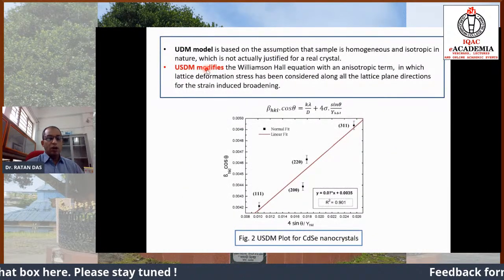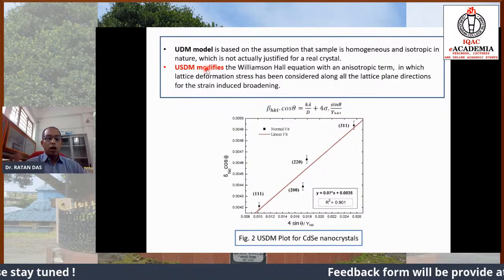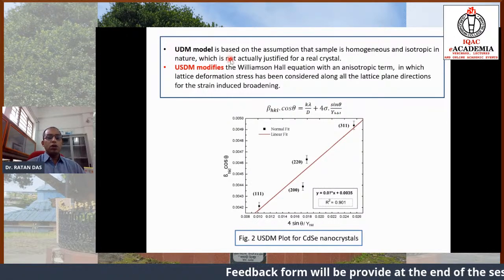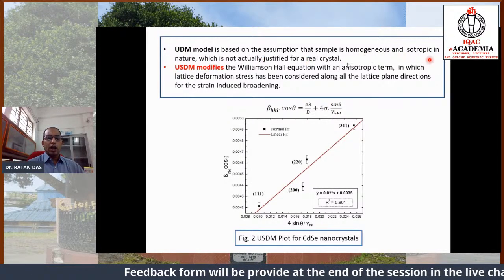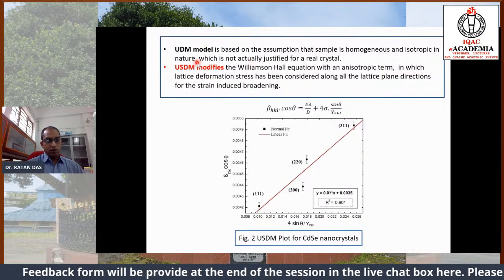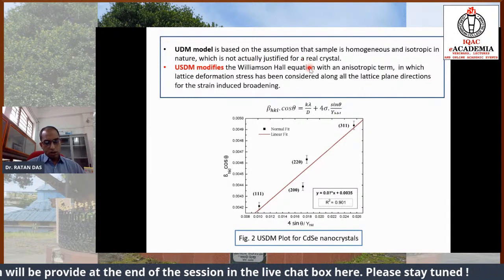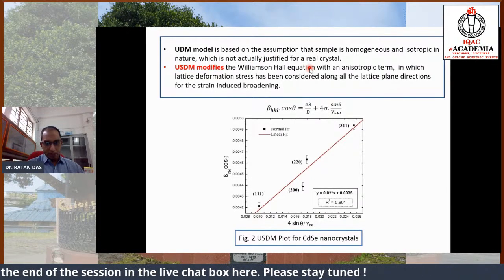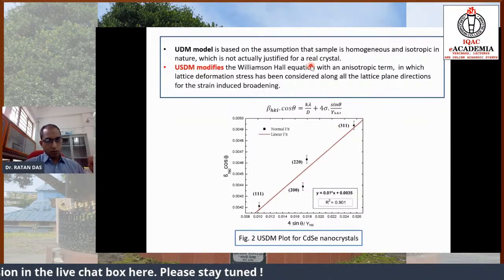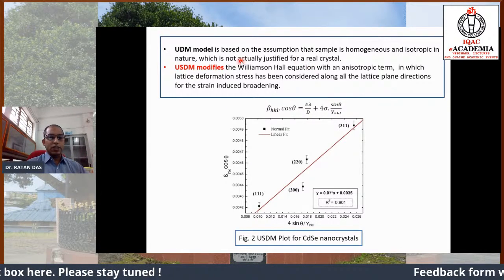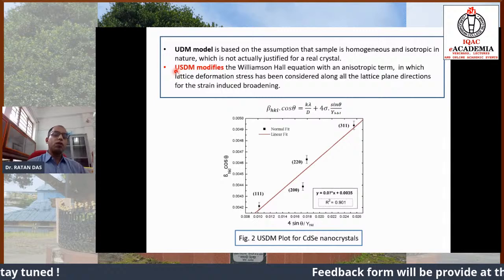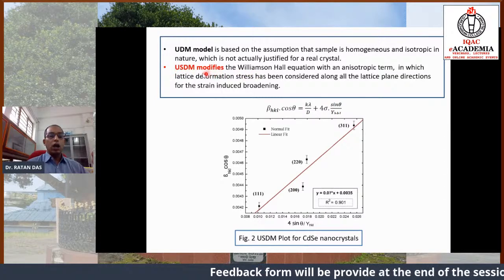Now, generally we modify the models actually. The UDM model considers the homogeneous or isotropic nature of the nanocrystals, where the strain is uniform in every crystallographic direction. But this is not the case for real crystals. This is the uniform strain deformation model.